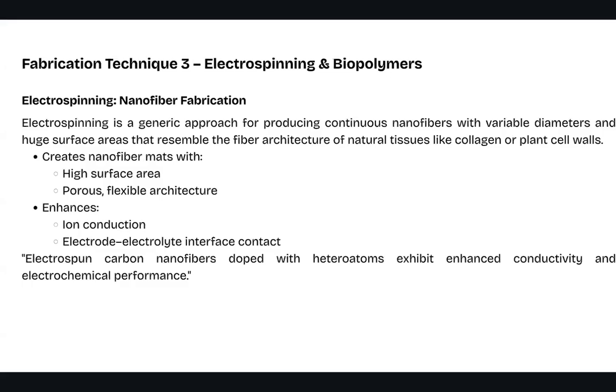So fabrication technique three. This is electrospinning and biopolymers. So what is electrospinning or nanofiber fabrication? Electrospinning is a generic approach to producing continuous nanofibers with variable diameters, and they have a huge surface area that resembles the fiber architecture of natural tissues, for example, collagen or plant cell walls. So it creates nanofiber mats with a high surface area, they're porous, and they have a flexible architecture. What does it enhance? It's going to enhance the ion conduction and the electrode-electrolyte interface contact. Electrospun carbon nanofibers doped with heteroatoms exhibit enhanced conductivity and electrochemical performance.